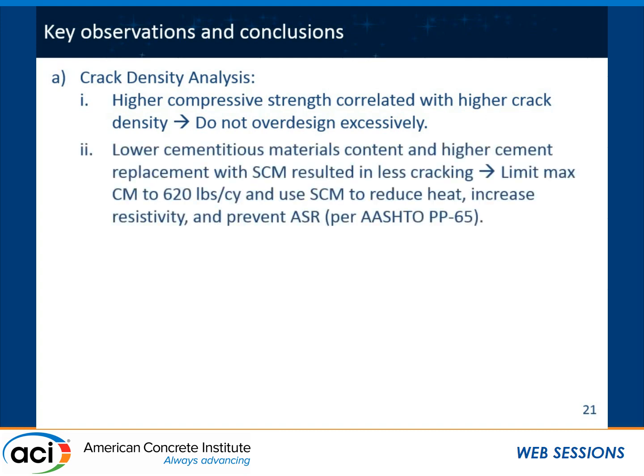The second one is that lowering cementitious materials content to the extent possible, probably through aggregate optimization and so on, and also increasing the cement replacement with SCMs, when it meets other criteria and to a reasonable extent, would result in less cracking.